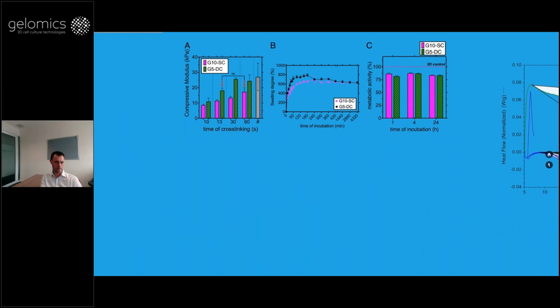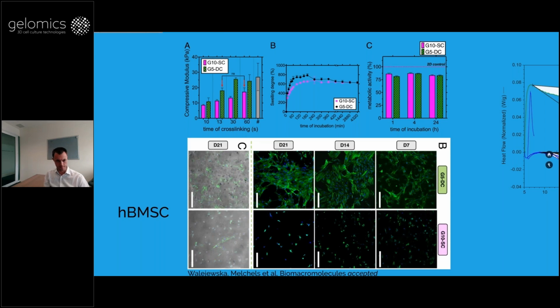Recently, together with Warsaw University of Technology, we compared them and looked at the effect on cells. So it chose a 5% pre-gelled, UV visible light photocured, and just a straight, so it's the SC. And we saw, despite having exactly the same stiffness, same GelMA, that cells do respond very differently. So we saw a lot more stretching of the cells within the double cross-linked gel compared to the single cross-linked gel of the same stiffness. So that is very interesting.